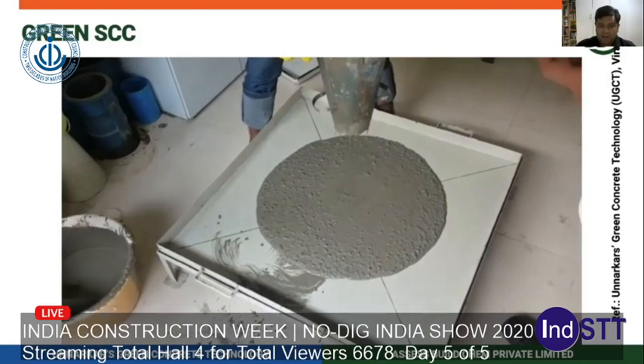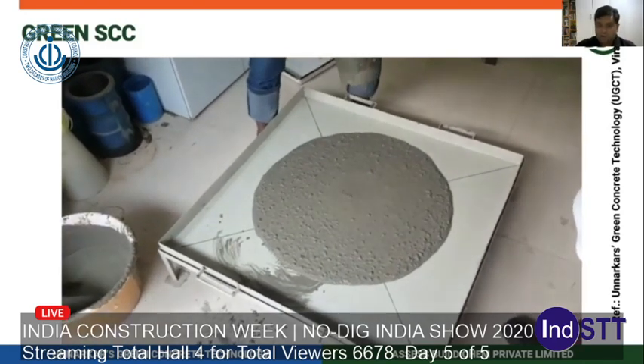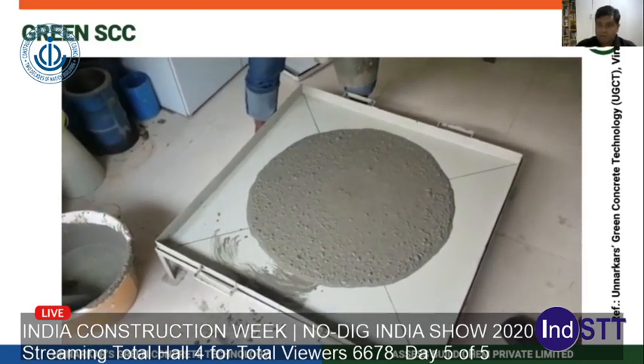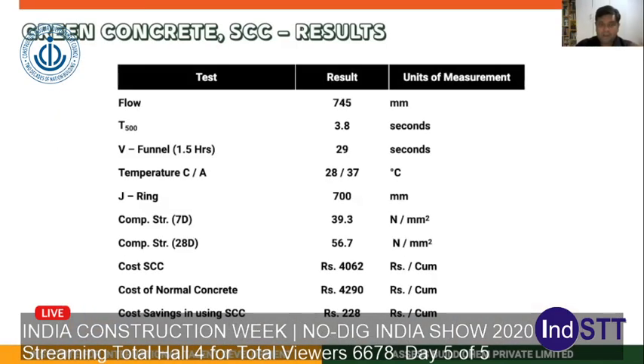After a lot of trials, I think we cast about 15 to 16 different mixes, and finally we could actually achieve SCC. We made the mix that met the requirements of flow, the T500 time, and the V funnel time. It passed through beautifully through the J ring, and in terms of compressive strength and everything, the mix behaved absolutely beautifully.